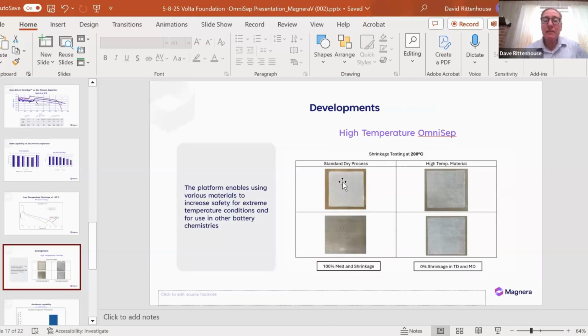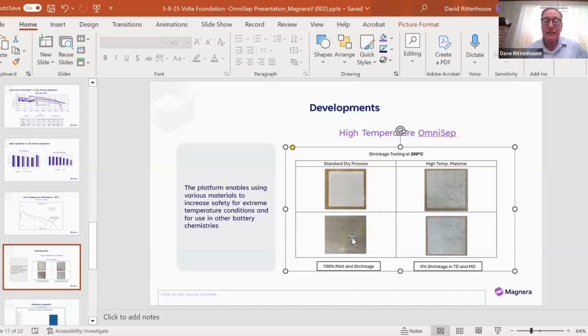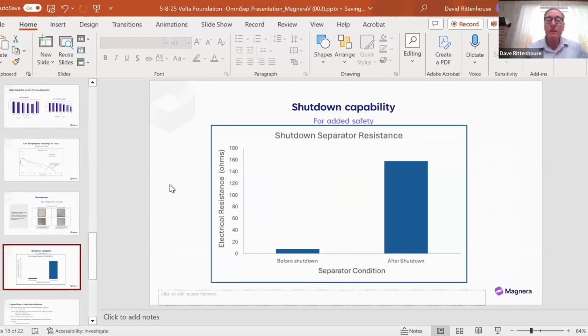I mentioned the high temperature development. We have several different separators that we've made that withstand 200 degrees. This is the standard dry process stretched film separator, polypropylene based. This is the OmniSep high temperature. After 200 degrees for an hour, zero shrinkage in the MD or TD, and these two little dots right here are the molten little blobs of polypropylene of the stretched film.